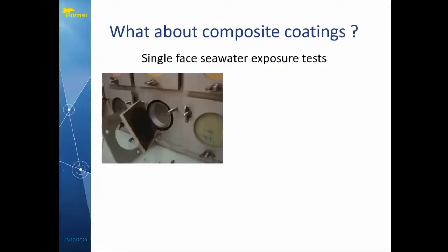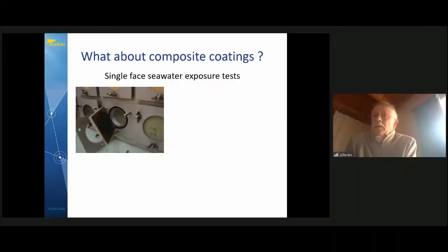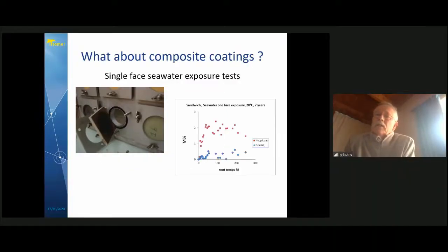One question which is often asked is, okay, you do a lot of these tests, you do them on small coupons and you do them uncoated. So what happens when you put a coating onto your composite? That's surely going to stop water ingress. So in fact, we developed single face seawater exposure tests to look at this.